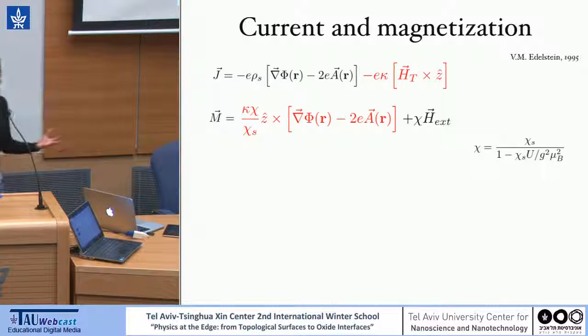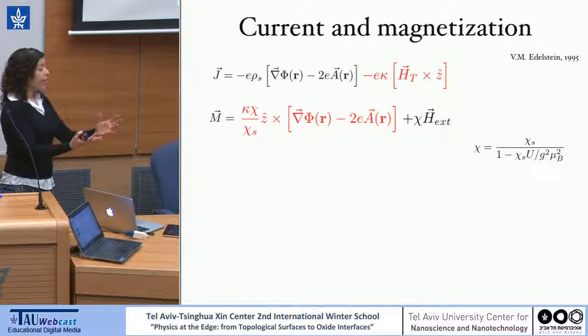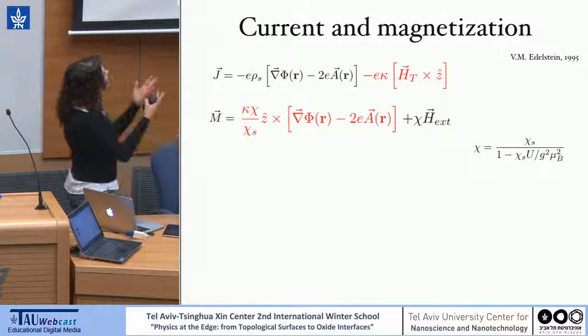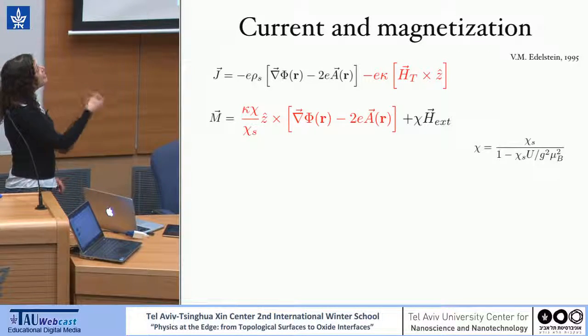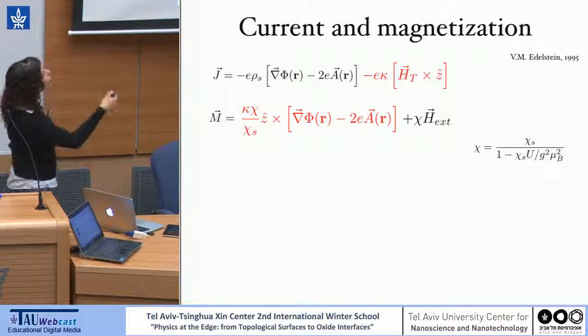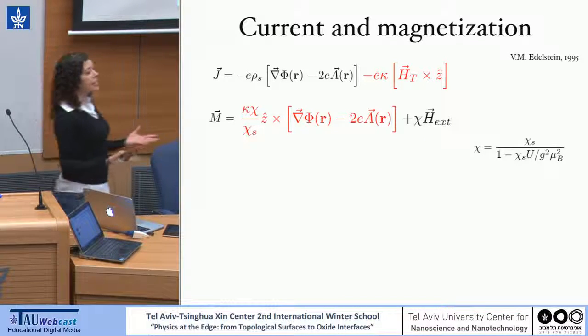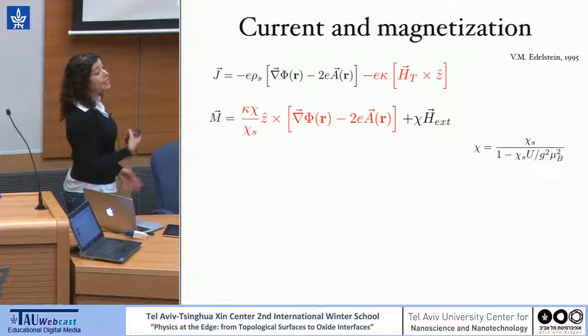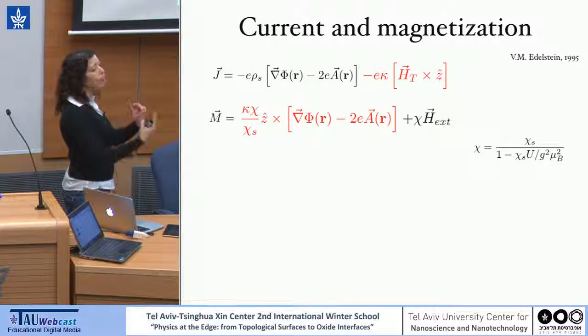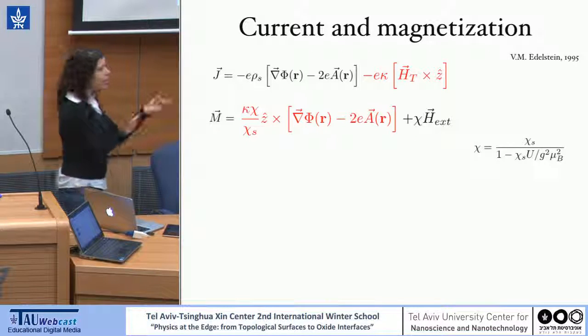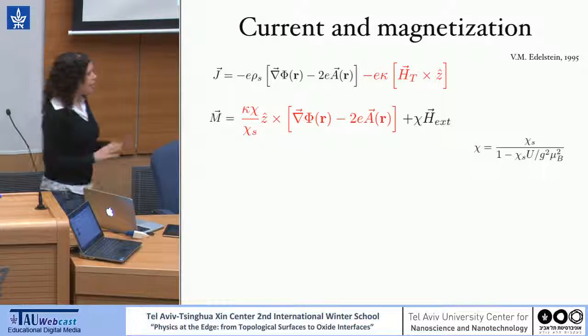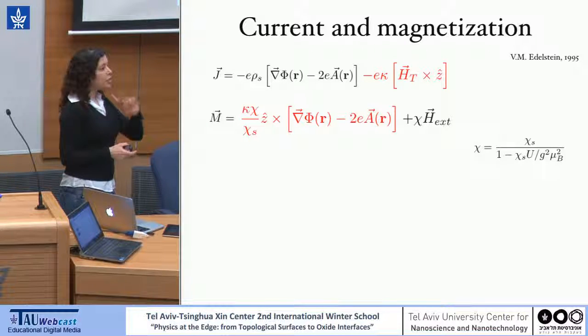In a simple way, we know that when we have spin-orbit coupling in the system, again, current is not only just momentum. It is also modified by the spin. So that is, in some macroscopic way, the response of the superconductor or the current of the superconductor is also modified by something which is spin-dependent, either total magnetization or external magnetic field. And the same way, the magnetization is now also related to the fact that we have currents in the system. Each time we have current, it must be followed by magnetization. And direction is a matter of whether it's Rashba or Dresselhaus, but once you assume Rashba, then each time that you have current, you have magnetization perpendicular to it.